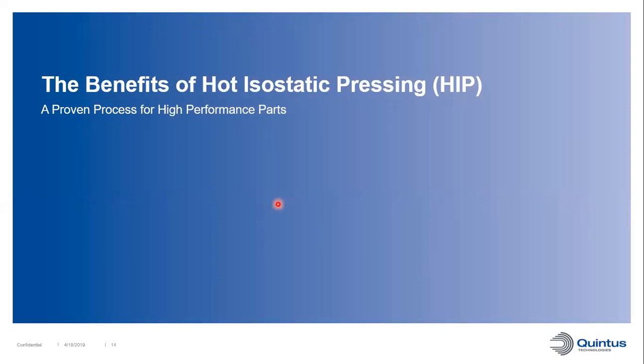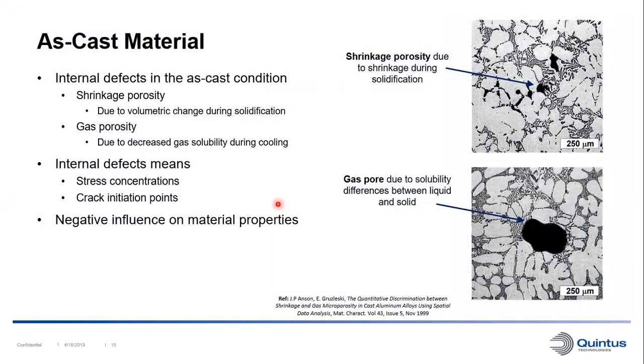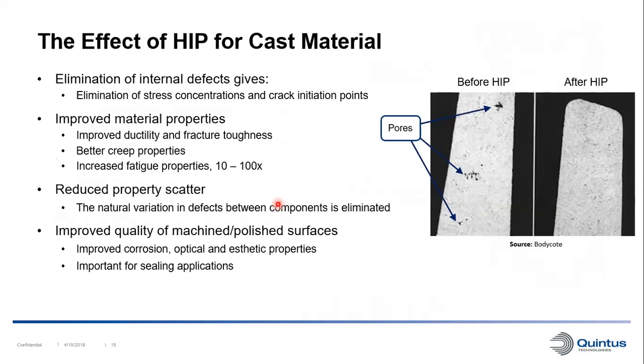And now I want to cover some of the benefits of hot isostatic pressing. As-cast material typically has some internal defects, such as shrinkage porosity due to the volumetric change during solidification. Also, gas porosity is pretty common due to the decreased gas solubility when the melt starts to cool and solidify. What these internal defects do is that they act as stress concentration and crack initiation points in the material, and that can negatively influence your material properties. So the main purpose of HIPing is to eliminate these defects, so we eliminate the stress concentration and crack initiation points and get improved material properties.